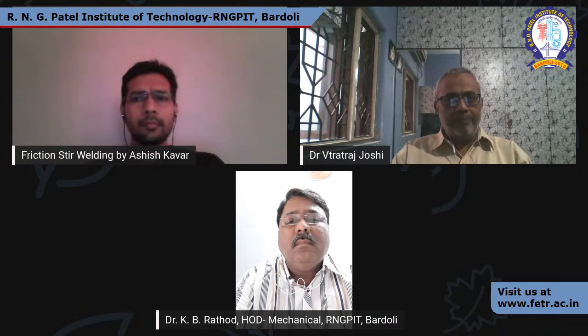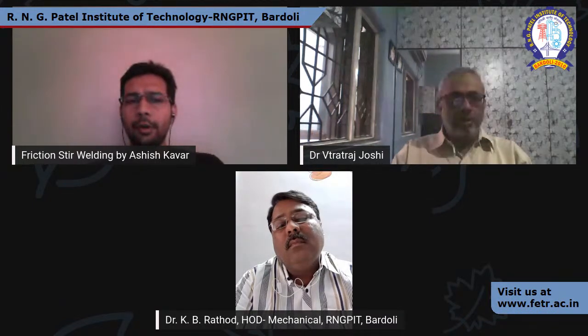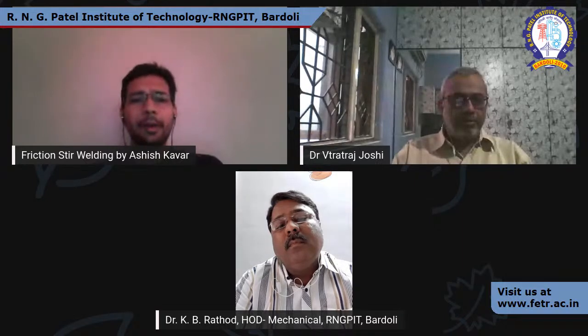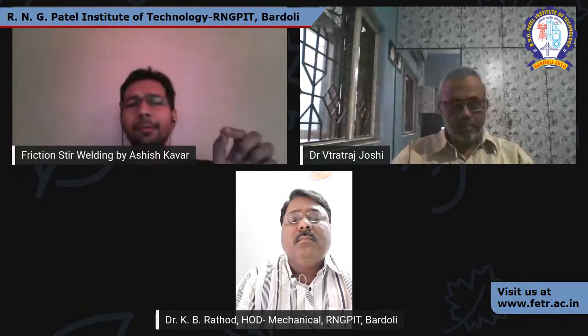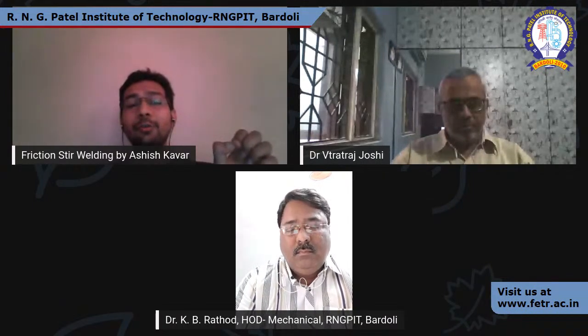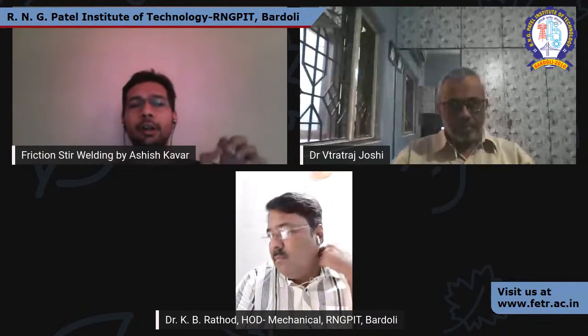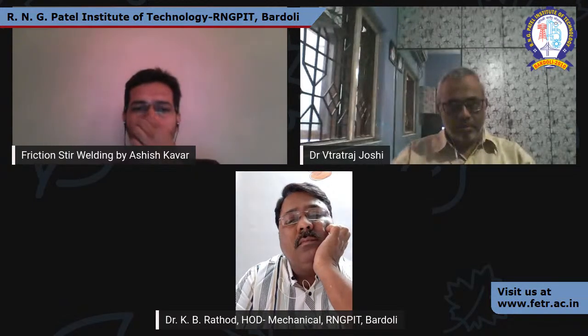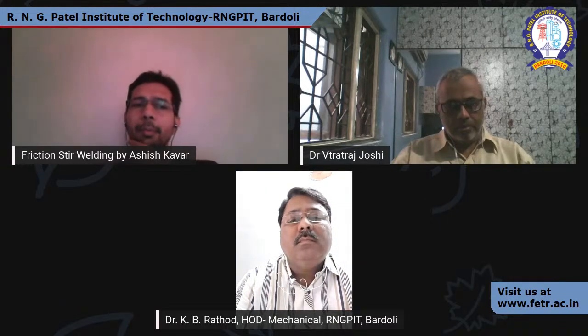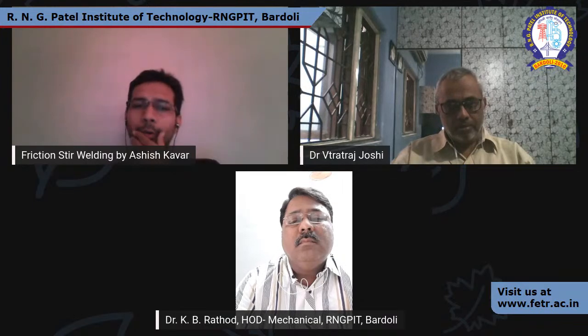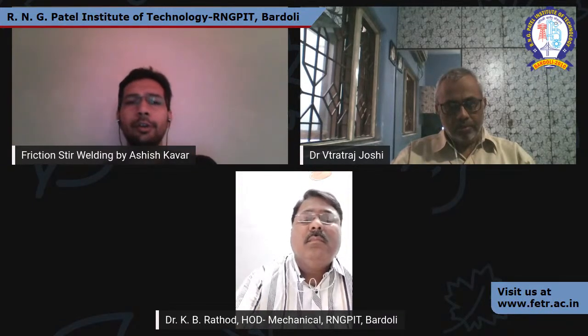And what is the effect of the depth of concave or convex geometry? So, sir, depth of cut, or we can say the axial force, is affected a lot in friction stir welding. Whenever we go with the advancing side, if the thickness of the material is around 5 millimeter, it is a square plate, then definitely our depth of cut is less than the actual thickness of the material. So, if the thickness is 5 millimeter, then we need to carry out the experiment with a depth of cut around 4.5 or less, or nearby 4 millimeter. So convex and concave also affect it, sir.